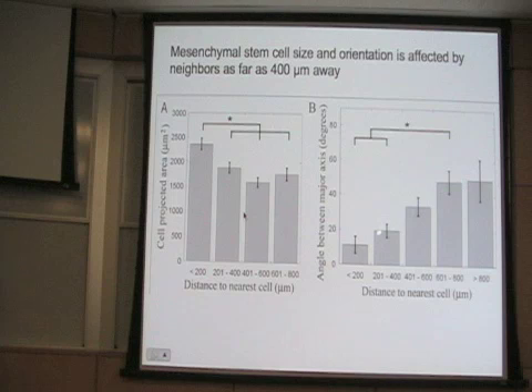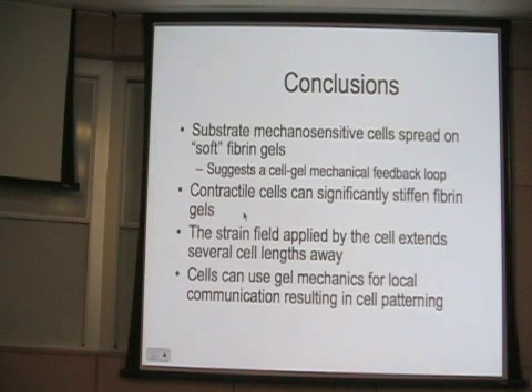And they become more oriented. So the angle between the long axes of the cell is quite small if two cells are within a couple hundred microns. It dissipates to sort of a random distribution only when you get more than half a millimeter away.